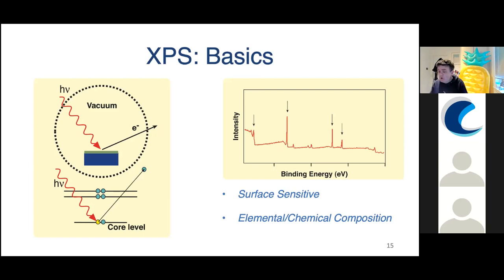Also, it can tell you more details. It can tell you the chemical composition. For example, for iron, it can tell you whether it's metallic iron, or it's iron that's oxidized to Fe2+ or Fe3+. And to emphasize, this is a highly surface sensitive technique, so it's well suited to looking at thin layers of corrosion inhibitors, monolayers or bilayers, because it only probes the top few nanometers of the surface. So we're really getting surface information here.